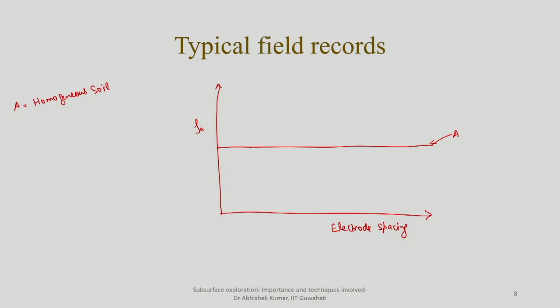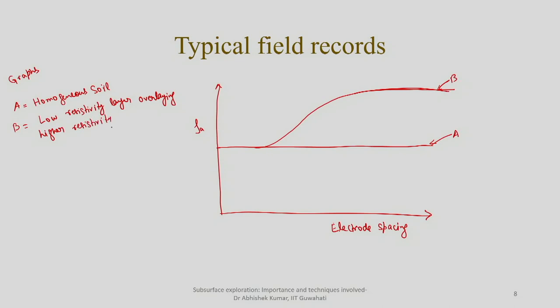Second, you can consider the resistivity increasing with respect to depth. B should be like this. So, graph A is indicating the resistivity is constant, that is homogeneous soil. B is indicating a low resistivity layer overlaying a higher resistivity layer. So, initially you had low resistivity and then higher resistivity, that is why you can see an increase in the resistivity with respect to the spacing or with respect to the depth.